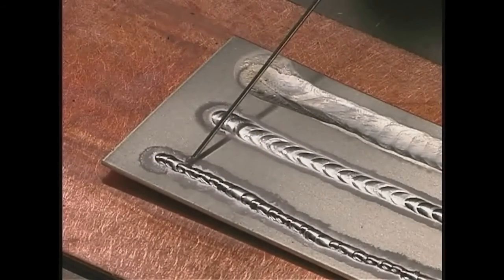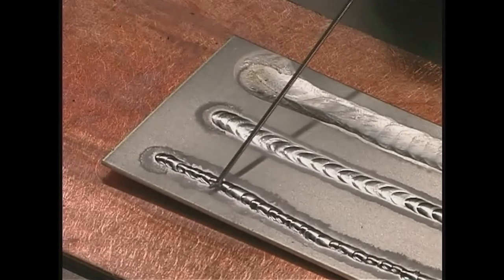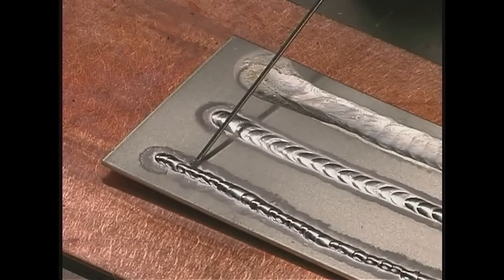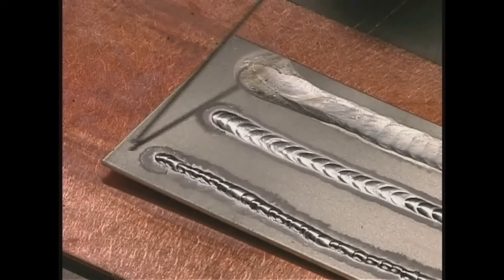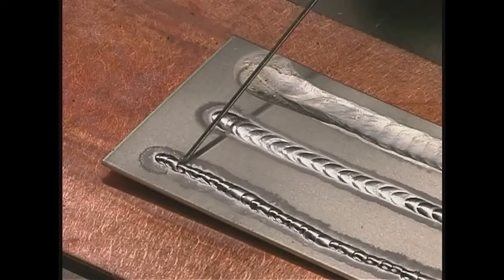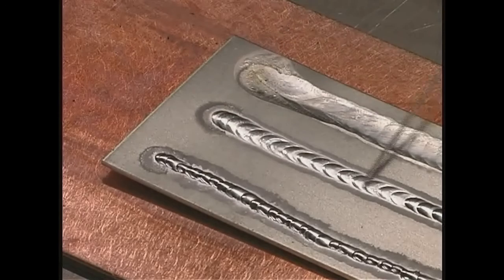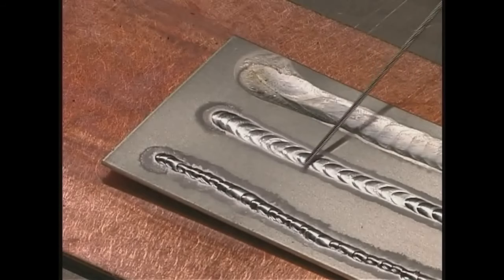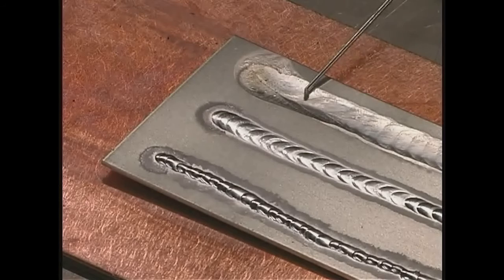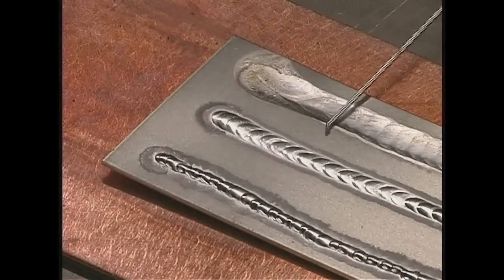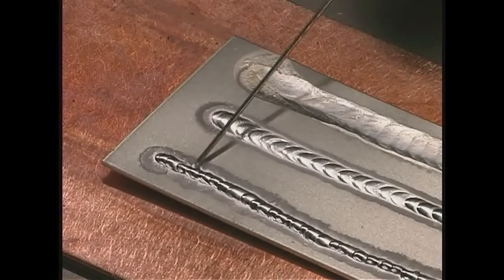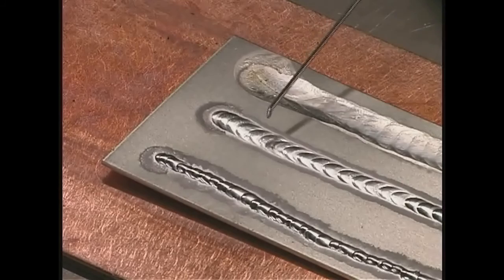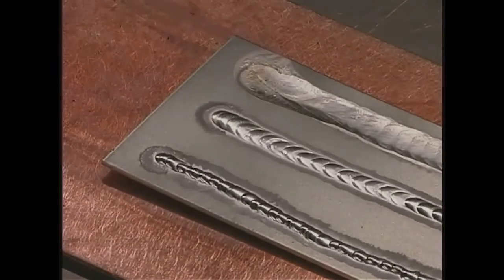So the first weld, which is too cold, doesn't really flow into the base metal around it well at all. It's just like the bead is resting on top of the metal like a worm. So this is the characteristic of a weld bead made with not enough heat. This bead is just about right. It's nicely rounded. You can see distinct ripples in the weld bead, and it flows in nicely to the metal next to it. And this bead, where there was too much heat, doesn't have any definition of the weld bead at all, and it's almost flush with the metal. So, pretty good example of too little heat, just the right amount of heat, and too much heat.